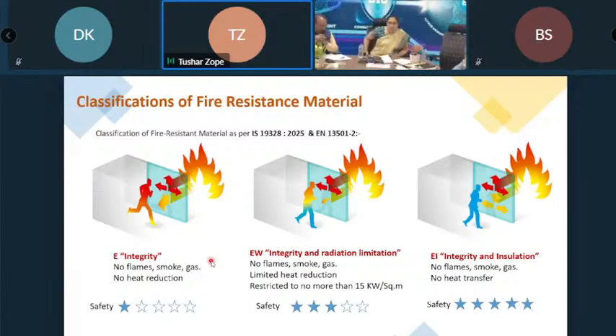The auto ignition of material present outside the glass in the exposed area can also occur, and it may burn the person if the heat radiation is too high. So how to avoid it? We can go for the EI category, which has the same performance as the E category and, in addition, restricts the heat passage. So a person can easily evacuate while walking through that area. However, there is one more category, economical between E and EI, called the EW category. It has the same integrity features and, in addition, restricts the passage of heat. In the third case, there is no heat transfer. In the second case, there is heat transfer, but it is limited to 15 kilowatt per square meter. And the person can actually run through that area and safeguard their life.